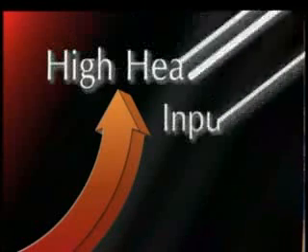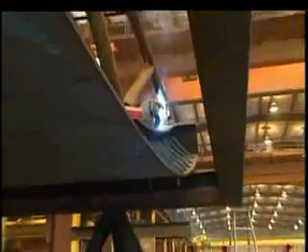High heat input is required for spray transfer. Because the weld puddle is large and fluid, the process can only be used for flat or horizontal welding. Due to higher heat inputs, spray arc can cause undercutting. The spray arc process has a very controlled, stable arc with little spatter and minimal shorting. Molten metal streams from the electrode end. The magnetic field from the arc surrounds the wire, and the high magnetic force from that field pinches the wire down at the end, so molten droplets stream through the arc to the workpiece.